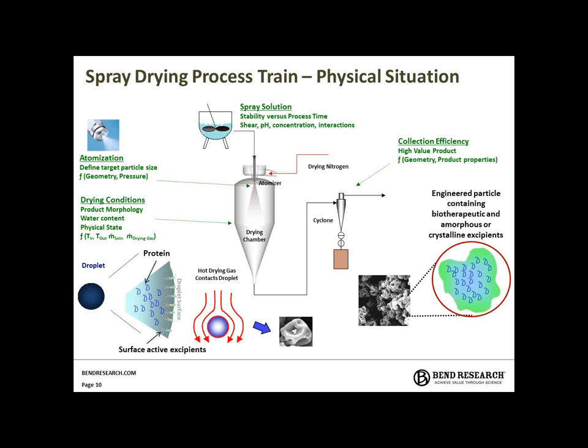Additionally, on the right, it's the collection efficiency, which often gets overlooked. A lot of these biotherapeutics are very high-value products, and the geometry of the cyclone can impact the collection efficiencies. So for a 2-micron particle for inhalation, you might use a different geometry as opposed to a 30-micron particle for intranasal or reconstitution purposes.